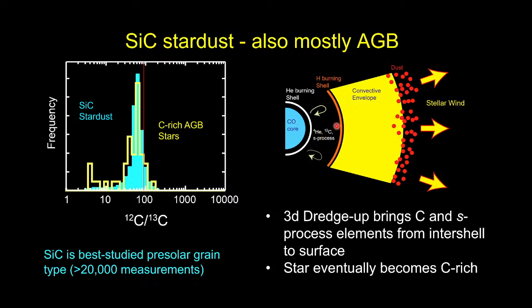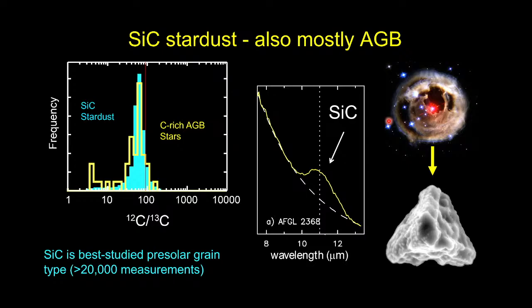And going back to this cartoon, the idea is that you're making a lot of carbon here in this region from the helium burning shells making carbon. That gets mixed into the envelope, and eventually the star becomes carbon rich and that has more carbon than oxygen. And that's when you start making things like graphite and silicon carbide that we find in these meteorites.